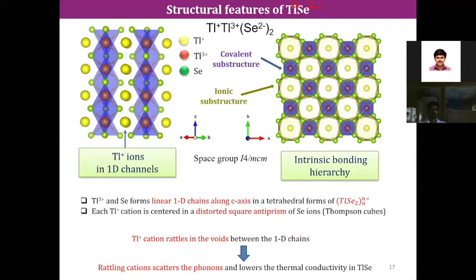So now what we propose from our chemical intuition or physical intuition is that thallium plus 1 has a weaker bonding and a lone pair, so it has an intrinsic instability. Because of this instability, the thallium plus 1 rattles back and forth in this channel, and this rattling can give rise to low energy optical phonon modes. This slow vibration of thallium plus 1 can give rise to very low energy optical phonon modes.